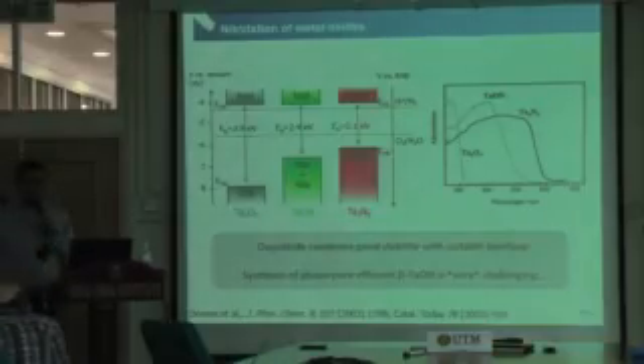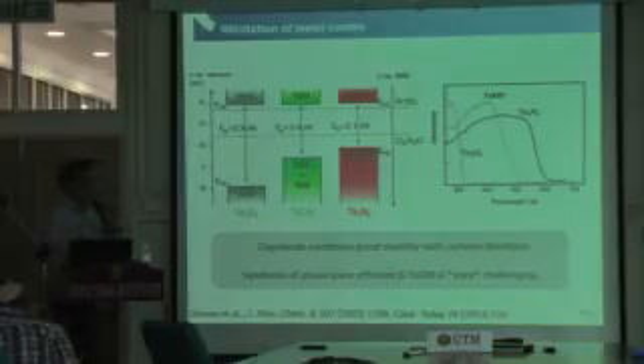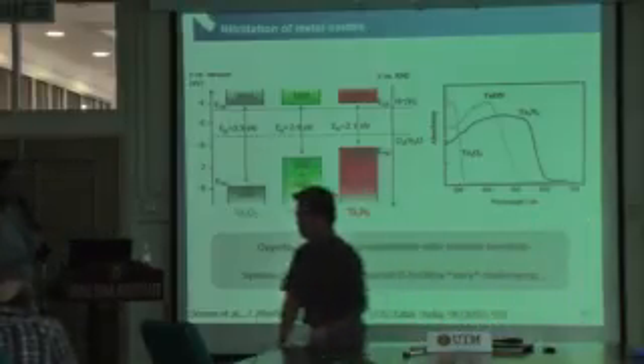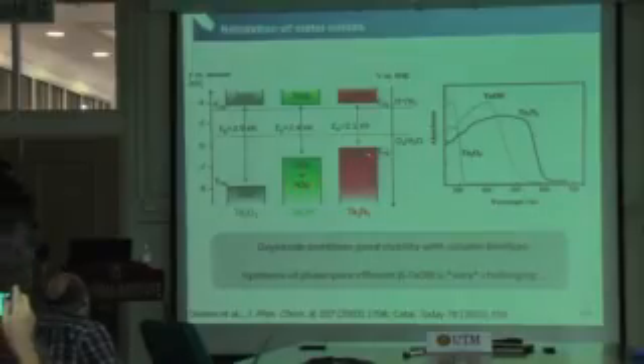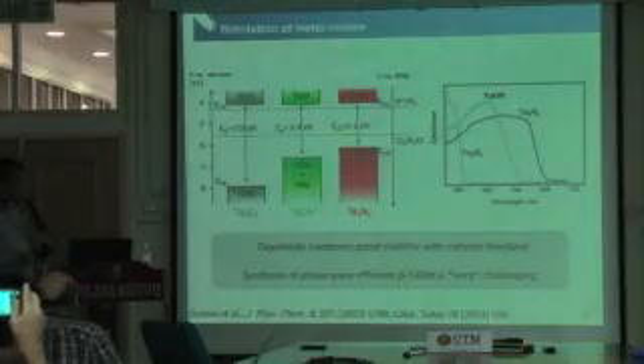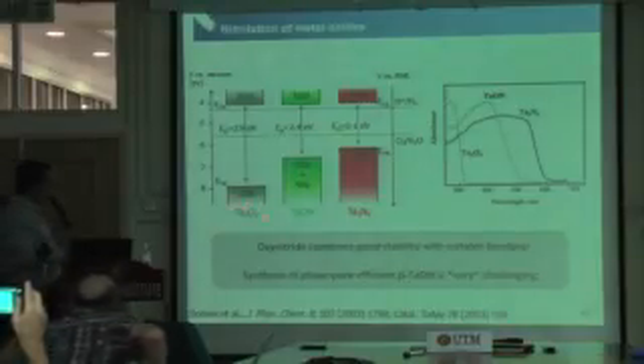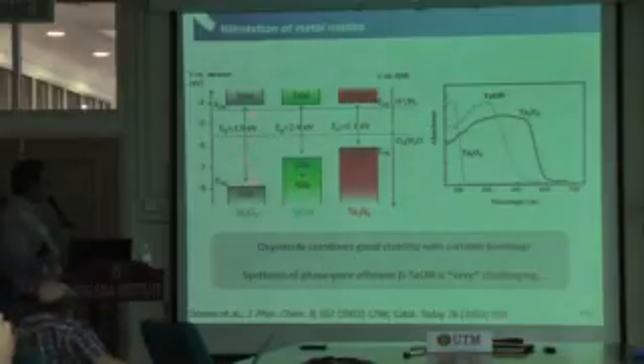Right, another option to actually decrease the band gap for oxides, if you don't want to find new oxides, is we can just use the oxides that we have and then reduce the band gap. We can do that, for example, by introducing nitrogen, performing nitridation. And the nitrogen 2p orbital is located rather higher than the oxygen 2p orbitals. So if you take the example of tantalum oxide and tantalum nitride here, tantalum oxide has a band gap of 3.9, and tantalum nitride, because of the nitrogen 2p orbitals, has a band gap of 2.1.